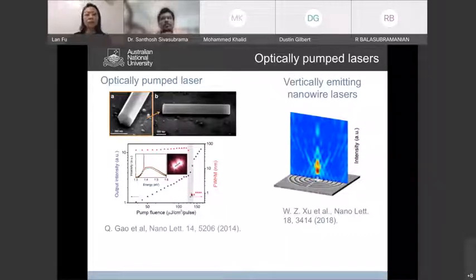So finally, I've shown that you can do detectors and solar cells, and nanowires by nature are also very nice laser structures, because they have a nice end facet when you break them off from the substrate, and thereby when you pump it, it can form a nice Fabry-Perot cavity, and then you can achieve lasing from those nanowires. So this is a really good demonstration of the good material quality of the indium phosphide nanowires grown by the selective area growth technique, which I've shown here.